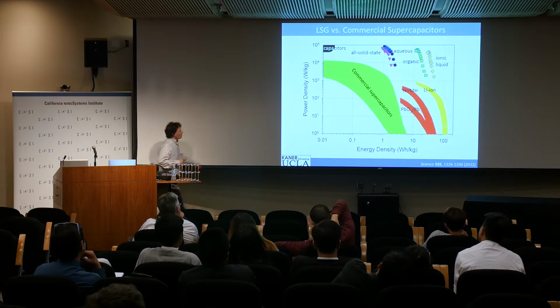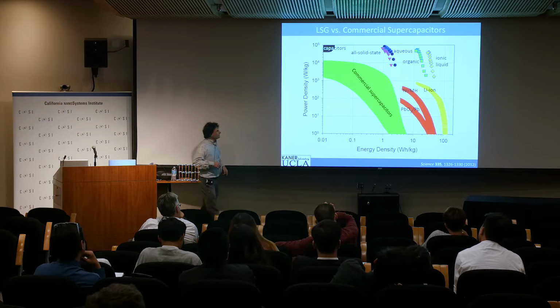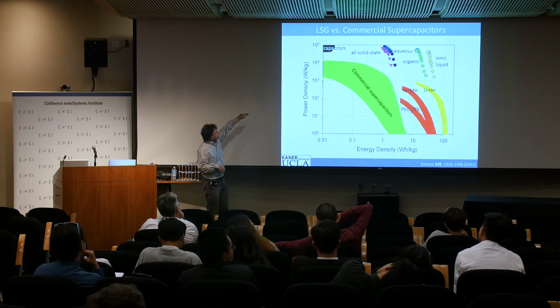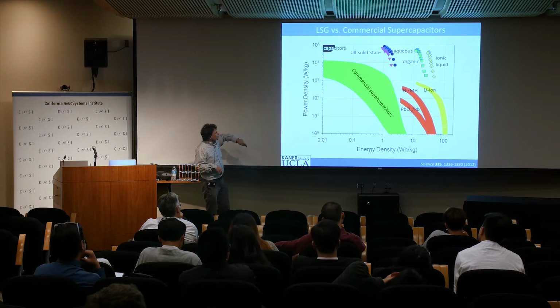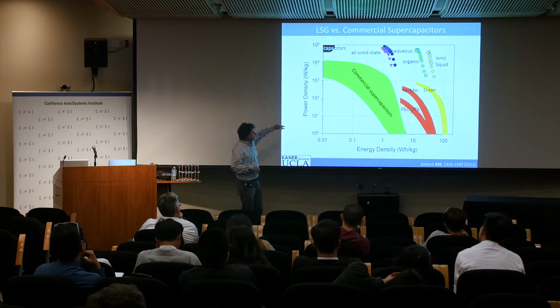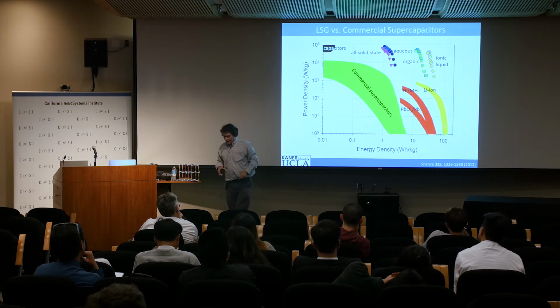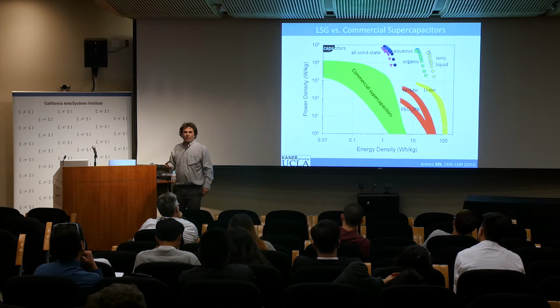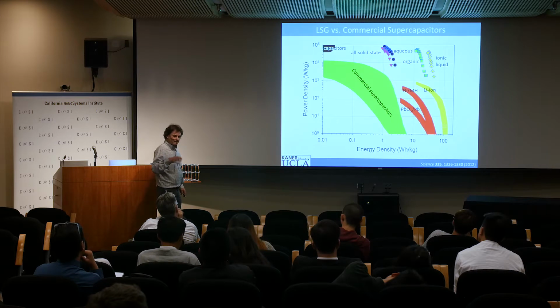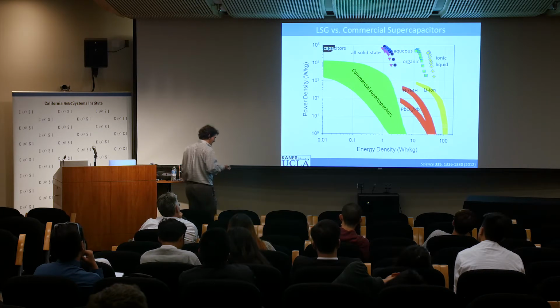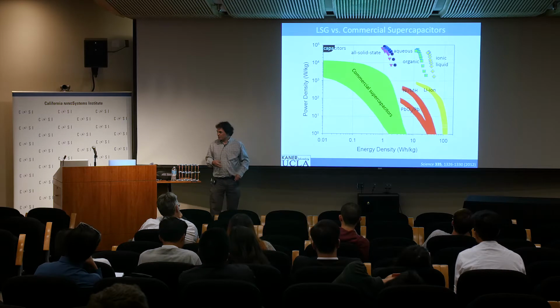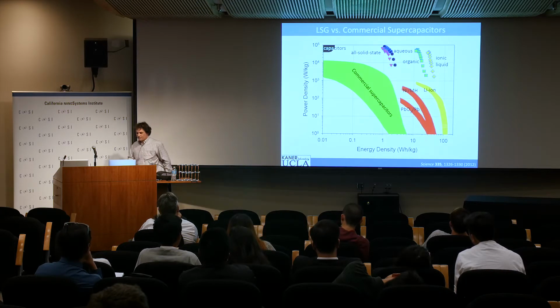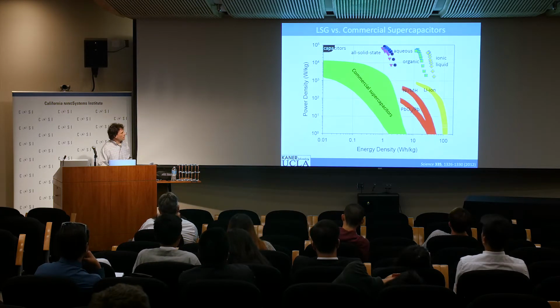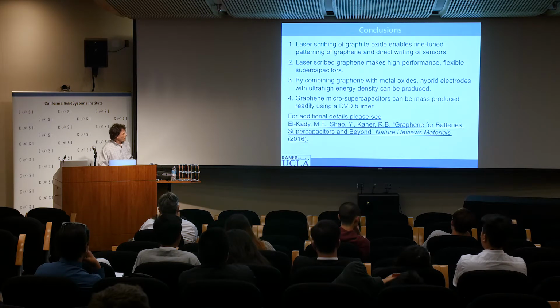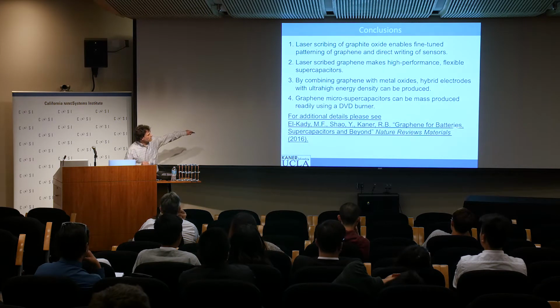And if you put this on a Ragone plot, power density versus energy density, here's our aqueous cells or organic cells and ionic liquids. So they already start approaching the energy density of lead-acid batteries. And in the future, what we've been working on is putting battery materials into these, and now we can start approaching the energy density of lithium-ion batteries. But we think that graphene is a really good way to improve almost anything that involves electrochemical and energy storage. And if you want to read more, you can see this graphene for batteries, supercapacitors, and beyond.